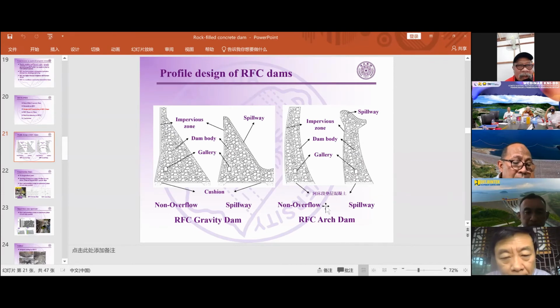All right. So my question is, in our case for concrete dams, we always have to pay attention to how permeable the upstream face is. And in some cases, we can use different kinds of material for the impermeable layer, for example, grout-enriched vibrating concrete, conventional vibrating concrete, or geomembrane. What is your guarantee that using self-compacting concrete, or even high-performance self-compacting concrete, the permeability will not create any problems for impermeability on the upstream face?